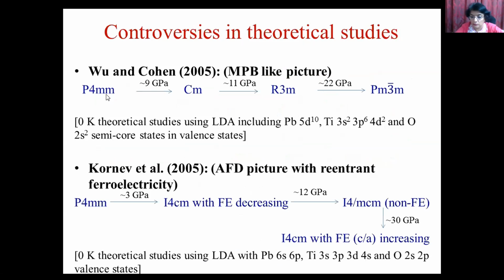When we talk about recent theoretical studies, there is a group which has presented the MPB-like picture. They say that the tetragonal P4mm phase transforms to monoclinic and then rhombohedral and cubic-like phase with increasing pressure, which supports the polarization rotation. And the second picture, by the group of Kornev, says that the tetragonal P4mm phase transforms to I4cm, which involves the AFD transition, in which first the ferroelectricity decreases and then above a critical pressure it increases, with an intermediate non-ferroelectric-like phase.